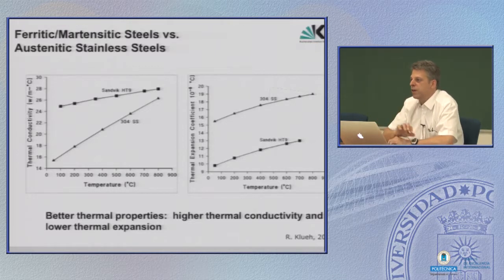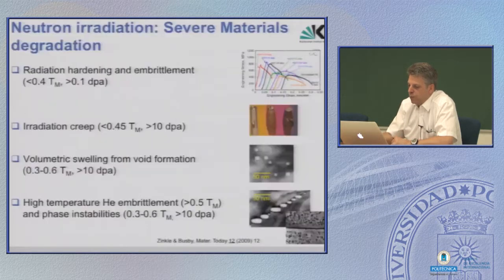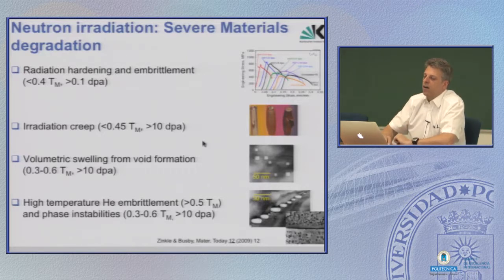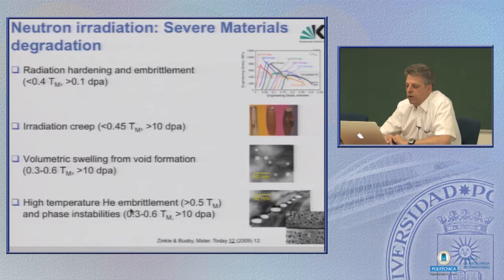So even if you don't look at neutron irradiation damage, basic properties of these materials favor 9% chromium steels. By now you know all about neutron irradiation and materials degradation. These are in principle the 4 points we always have to keep in mind: the hardening, the irradiation creep, the volumetric swelling in materials, and the helium embrittlement.